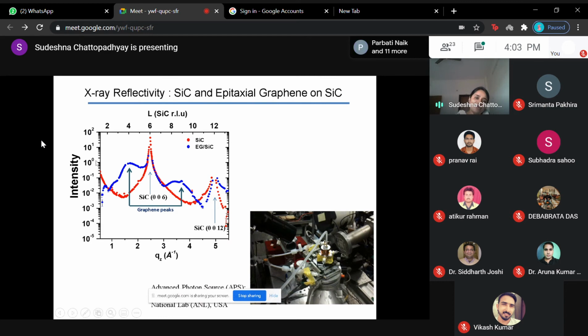So for the single layer, I am telling you single layer of graphene because we fit the data. This hump you can fit with the crystal truncation rod theory model, which we used to use, and I'll show maybe afterwards for other things. From fitting these things, we can get the complete feature of where the silicon atoms are and where the carbon atoms are, even separations; a 0.6 Angstrom, 0.9 Angstrom kind of resolution we can get from this technique. So it is really a good technique for such a kind of system.